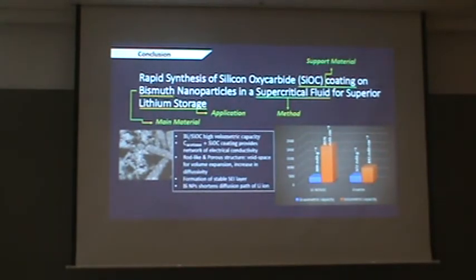To summarize, our research introduced a new technique in producing bismuth silicon oxycarbide composite by a simple method, just mixing silicon oil with the precursors for SiOC coating and also for carbon coating. Then for comparison with the conventional graphite, we also did a calculation on the volumetric capacity, and we can see that our sample provides more volumetric capacity compared to graphite.